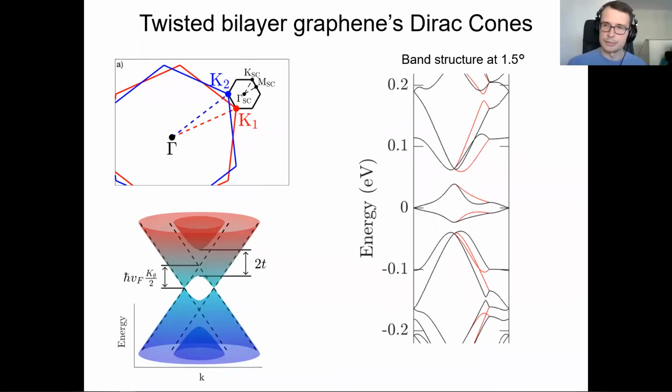That's correct. Yes. And it's very strange because in experiment, the AA is not small compared to the AB. That's true. It's about 30% smaller because of relaxations. But yeah, that's a pretty technical point, and that's why I didn't want to really talk about it. But that paper is not saying that you need that to be true for flat bands to exist. It just shows that when that condition is true, you can analytically derive the flat bands using complex analysis.